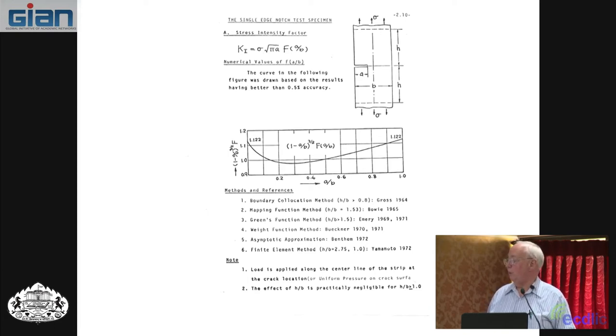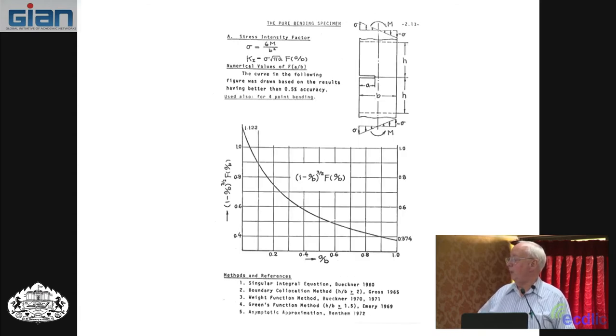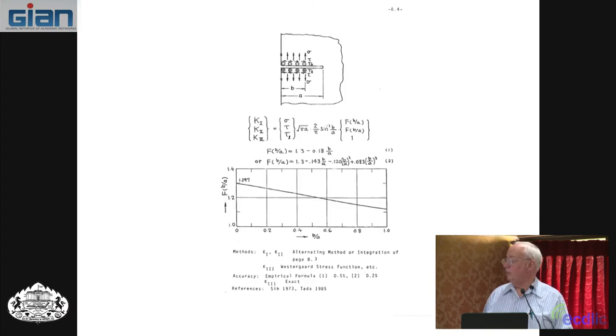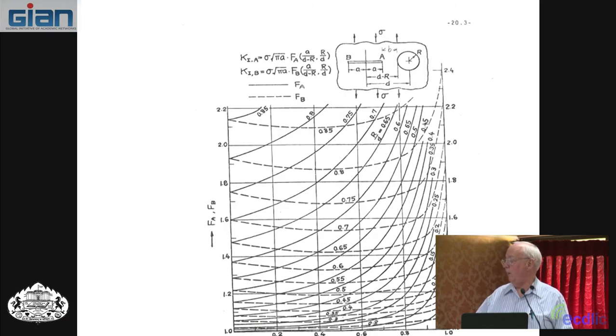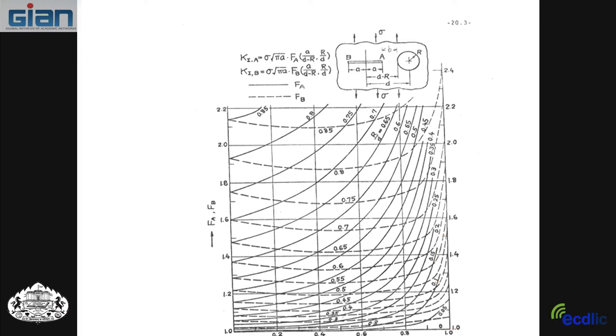Some of the others that we won't use much, but I'll just show you. Single edge crack with bending rather than tension, and in the limit it tends to 1.122. All edge cracks in the limit of a small crack compared to the width tend to 1.122, and all center cracks tend to 1.0. Some of the solutions from the handbook that we won't use, just to show you how complicated they look. Here's an example, a crack approaching a hole on one side and then the empty plate on the other. So you have the solution for the A side and the B side being different, and all these crisscrosses of curves.